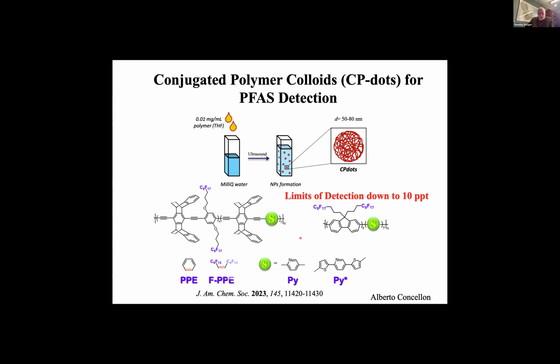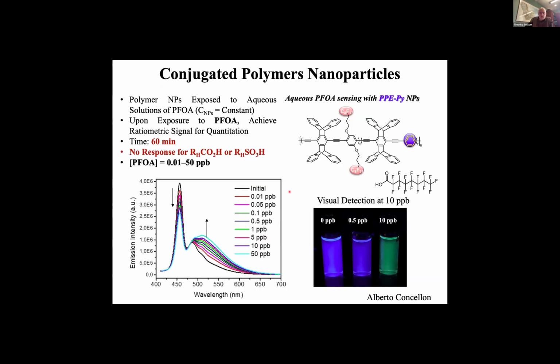So if we take these and we disperse them, and we can find that very simply with this method, we can get down to 10 ppt. We have actually other methods at a company that we founded that get down below that, but this is what our published methods are. And this is just showing what the data looks like.